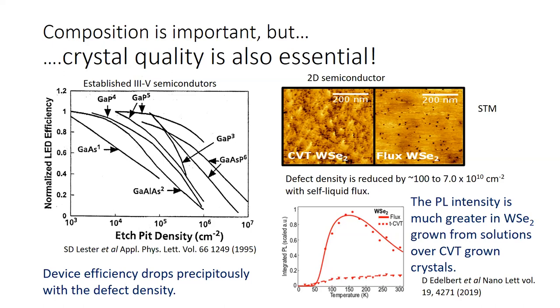So for example, on gallium aluminum arsenide, if you get defect densities above about 10 to the 6 per square centimeter, then your device is pretty much dead. And people are starting to recognize this for 2D materials as well. Jim Hone's group from Columbia has recently come out with a paper looking at tungsten diselenide and compared material grown by two techniques, the chemical vapor transport and also flux method. And in the flux method, defect density is 100 times less. And consequently, the photoluminescence is much more intense from the better quality material. So defects matter, and decreasing the defects is essential.